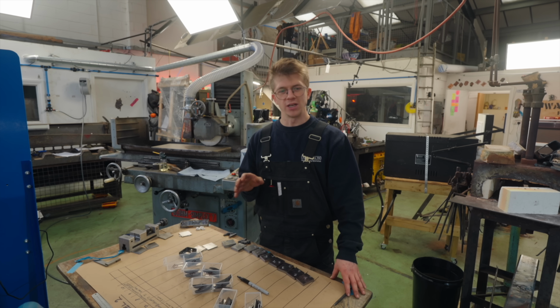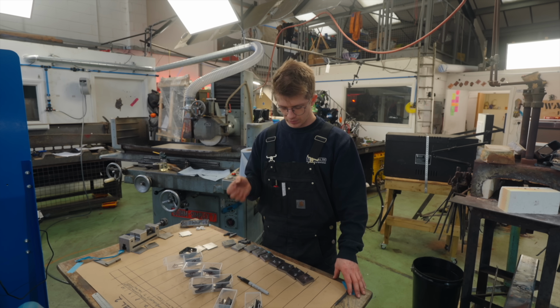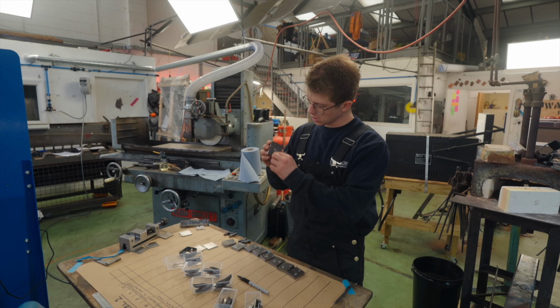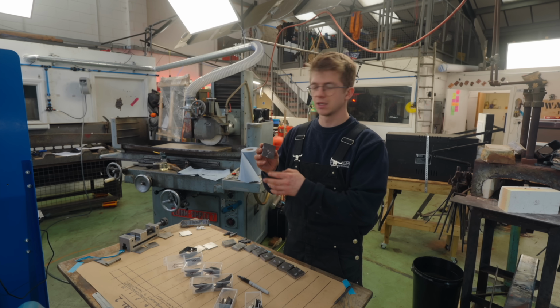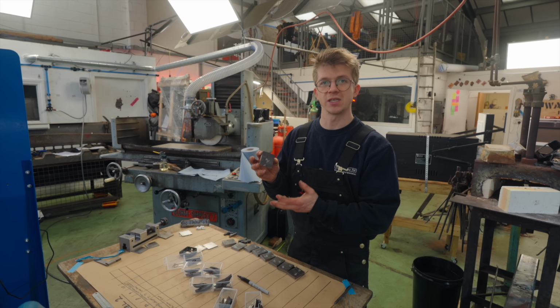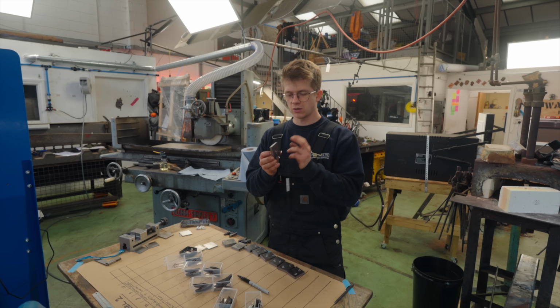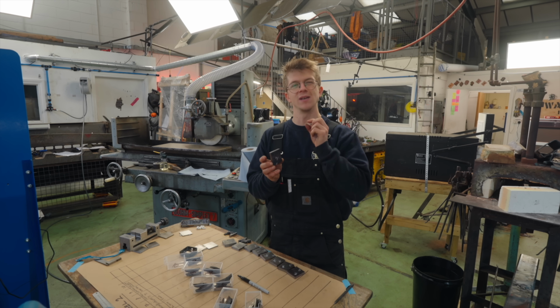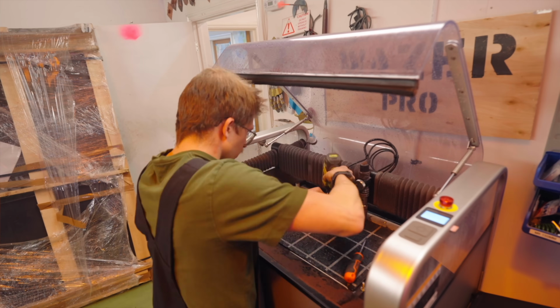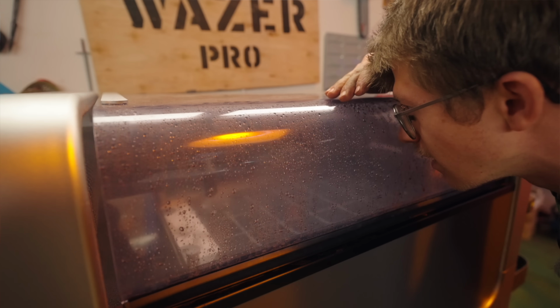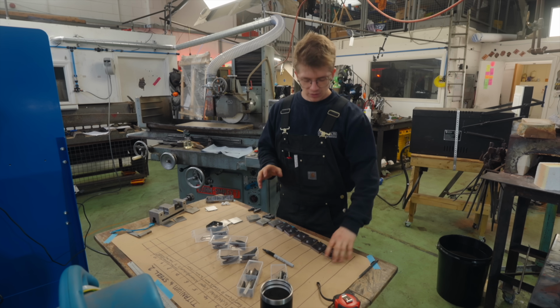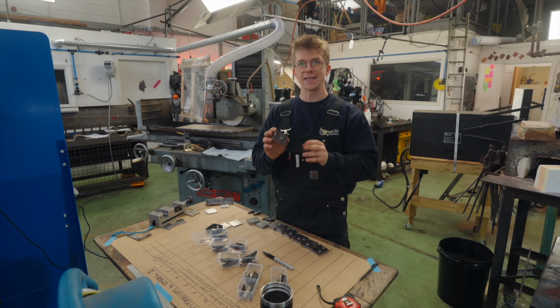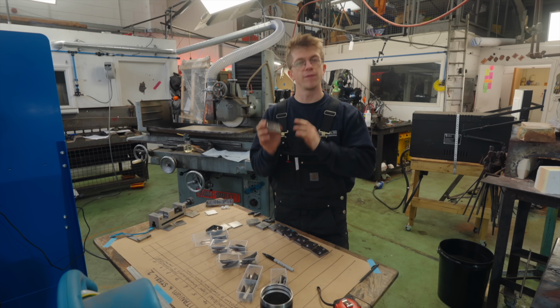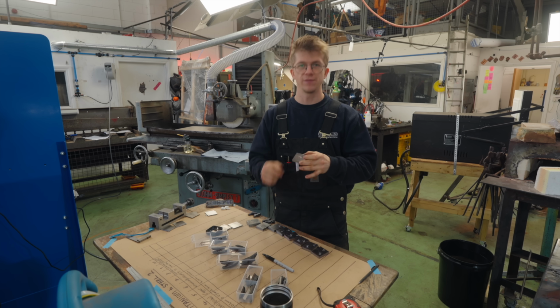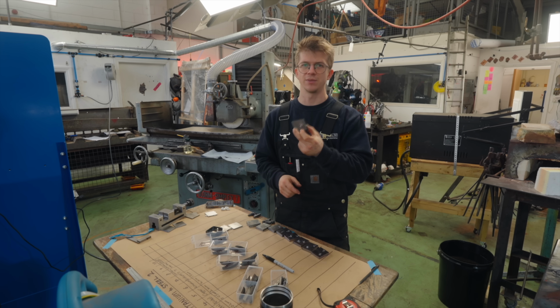In terms of order of operations, I'm at a little bit of a crossroads, because I am gonna want to slice these pieces into 3, so that we have 3 samples to test from. But we also need to break off the steel jacket and get everything to an even thickness. Last time on the water jet samples, we did it once they had all been completely cut down to size. This time around, I'm going to break off the steel jacket, mill them to thickness before cutting them into the 3 final pieces that'll give us 3 test samples from each one.